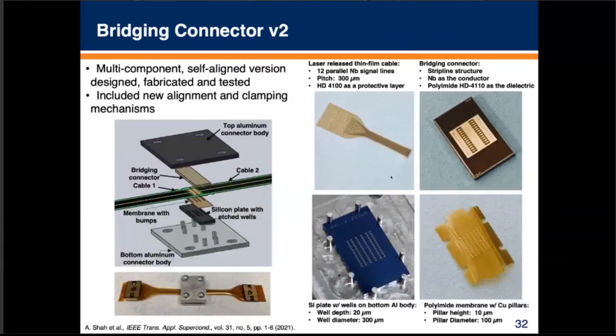For the next version, we tried to get a little fancy and have these extra little pieces that we hoped would be more uniform across the whole structure, and include some self-alignment features, both for the tapes as well as the components of the connector. You can see the tape alignment features here, and all of these were precision fabricated with microfabrication techniques, so we get down into the low tens of microns alignment. This consisted of several pieces of the tape and this connector structure, and in fact this is a full stripline that was fabricated onto that connector.